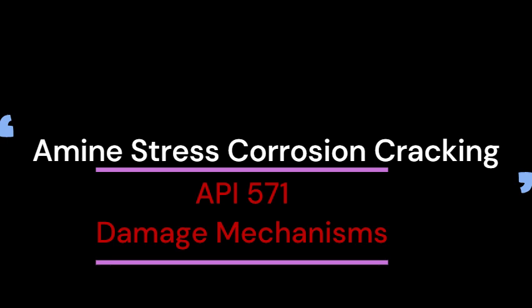In systems removing H2S, the H2S in the rich amine actually provides a sort of protective effect. It reacts with the steel surface to form a thin film of iron sulfide, FeS. A barrier layer. Exactly. That FeS film can help impede or slow down the amine SCC mechanism. So while rich amine systems aren't totally immune, especially if you have wet H2S corrosion issues happening separately, they're generally less susceptible to this specific amine-driven SCC compared to the lean side. Okay, that makes sense. Lean service is the main danger zone.